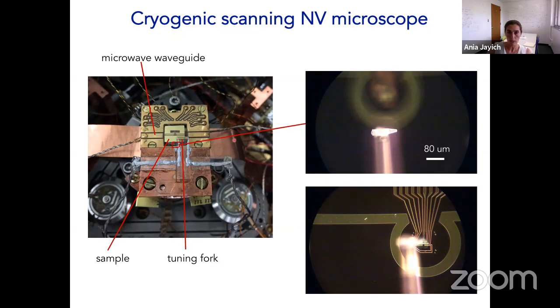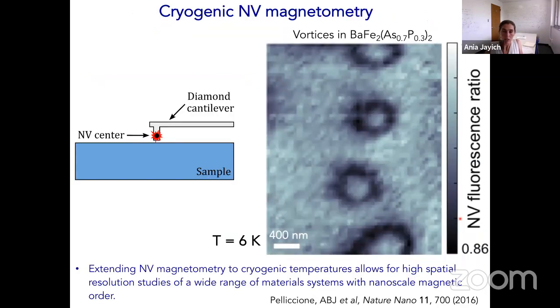It's a tuning fork based AFM with a diamond cantilever with little pillars on the end, which you can't really see here, but which we can position close to whatever sample we would like. In this case, this is just an optical image of a graphene sample with electric leads connected to it, and this big omega shaped thing is actually the RF delivery system. So this is what our cryogenic scanning NV microscope looks like, or at least a zoom in of the active area.